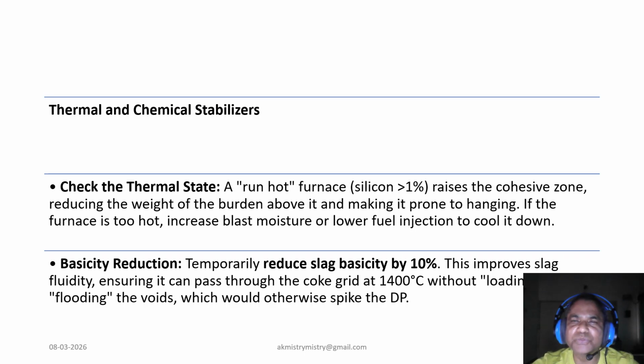Chemistry plays a huge role in pressure control. If your slag is too thick, it floods the void in the coke and spikes the dp. To prevent this temporarily, reduce slag basicity by 10%. Now this makes the slag more fluid at 1400 degrees centigrade, allowing it to pass smoothly through the coke without blocking the gas flow.